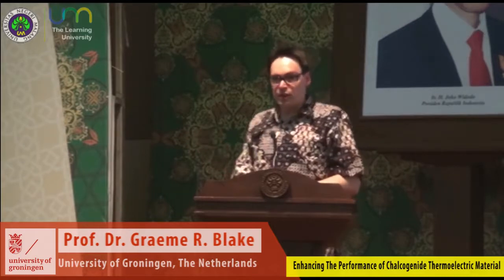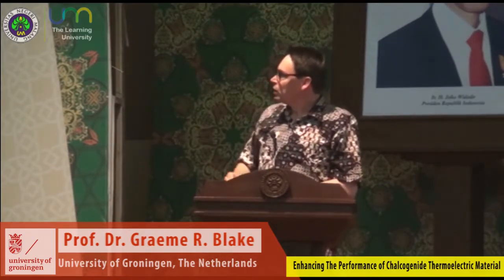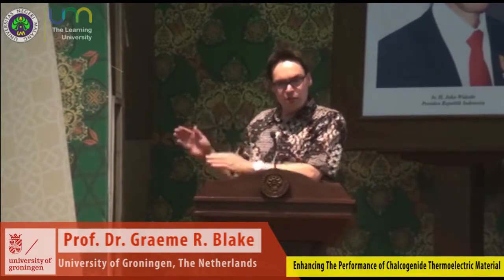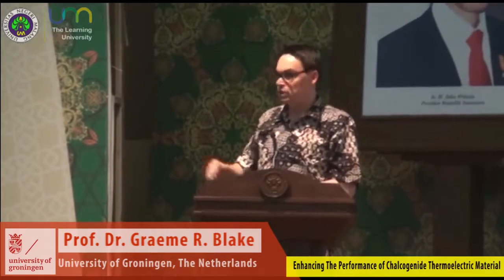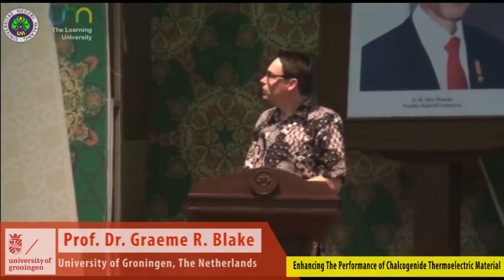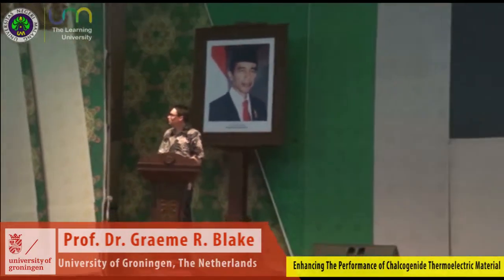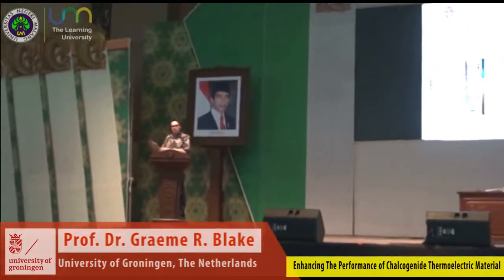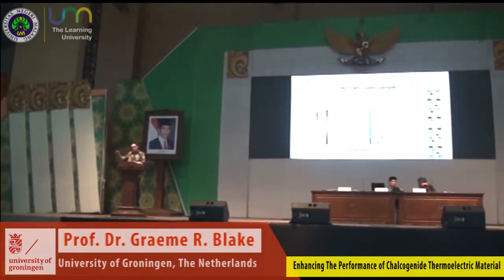So a similar thing happens in the cubic form of TAGS, which hadn't been reported before. We again get, this time, an irreversible phase transformation to a different trigonal layer structure, this time with 21 layers. And this time it appears to have a tellurium vacancy layer, 1 per unit cell. And again we have this spontaneous precipitation of the Ag8GeTe6 phase. And in this case it's irreversible. If we cool that back down to room temperature, we're left with the trigonal phase.